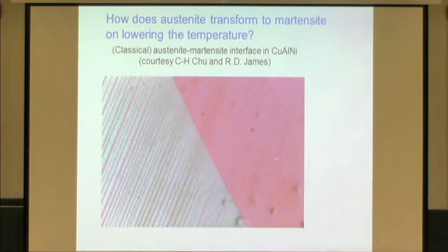And it can't make, as I told you, an interface between a pure variant of martensite with this. That's not possible geometrically. So it does the next simplest thing. It forms a simple laminate alternating between two variants. And if that's very fine, if you do a little kind of tweaking near the boundary here, boundary layer if you like, you can make that compatible with the martensite, and so that's what typically it does. And so according to mathematics then, the Young measure here would be a Dirac mass at the identity. Here it would be lambda Dirac mass A plus 1 minus lambda Dirac mass B, where A and B belong to the martensitic energy wells and are rank 1 connected.